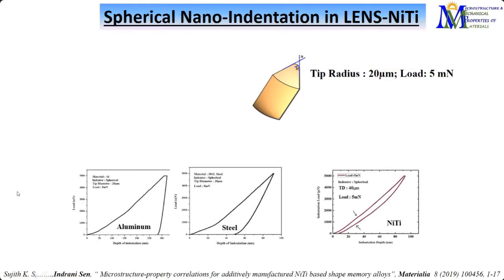What we mean by that is that we did nano indentation using, again, different kinds of parameters very specifically suitable for pseudoelasticity, which is beyond the scope of today's presentation, but you just need to understand that we characterized it with nano indentation to find out the local recoverability, the ability of the material to recover the strain that is being applied. In the case of aluminum, you can see that it is completely not recoverable. Huge amount of plasticity. We know that aluminum is very, very ductile. Steel has a little bit lesser.